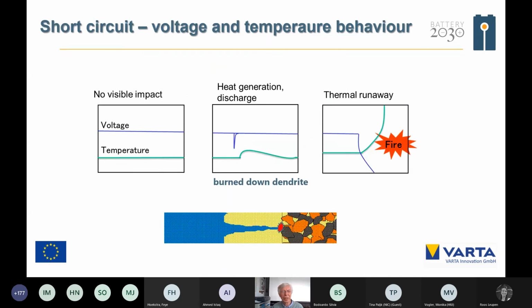The voltage, if you have a short circuit, normally the voltage is going down. And here we have a case, an example; not in every case will we find that. Here the dendrite is burned down. That means the dendrite is coming to the cathode, the voltage is going down, the temperature is increasing, and the temperature will be so large that the dendrite peak will be interrupted. So you have no more short circuit.